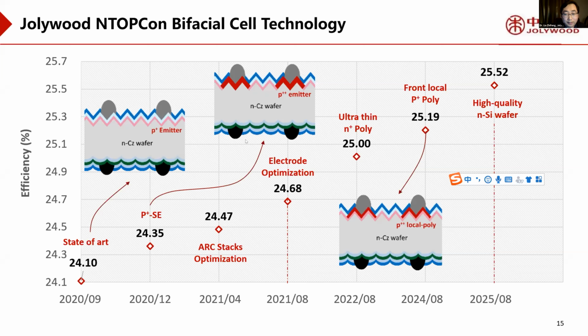Okay. This shows how we get 25% efficiency. This includes the P+ emitter. We use a selective P+ emitter, ARC coating optimization, and some electrode optimization, and especially poly optimization, using ultra thin N+ poly and so on, and also including local P+ poly. We hope you can get the efficiency to exceed 25%.